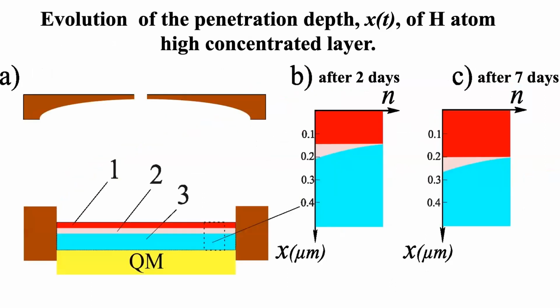How we can see this - also I didn't tell, we have always this high concentrated layer, which corresponds to the broad line. But we consider that low concentrated signal from the front of this layer, and this is low concentration layer. After 2 days, we have distance 0.14 micron, and after 7 days, we have 0.2 micron penetration of this layer for normal hydrogen.